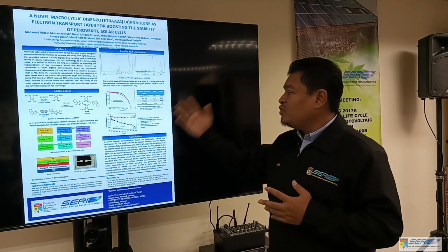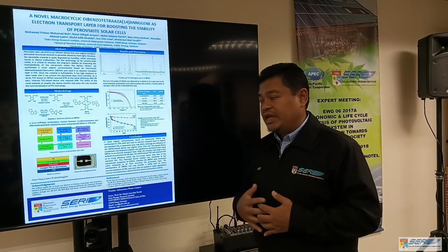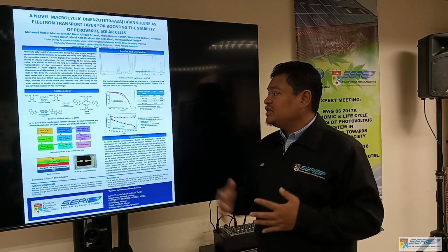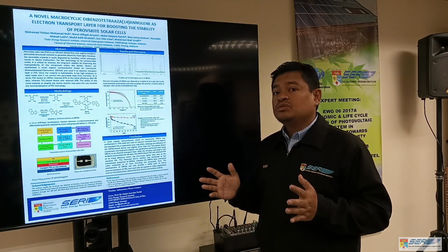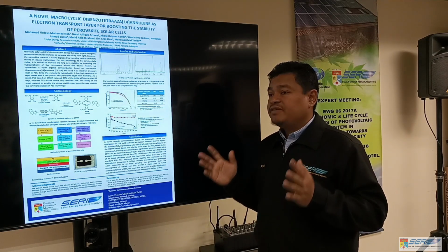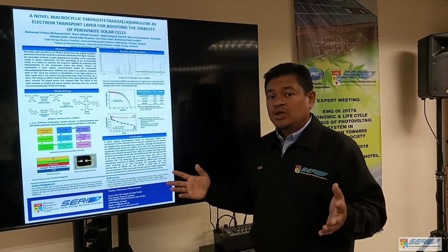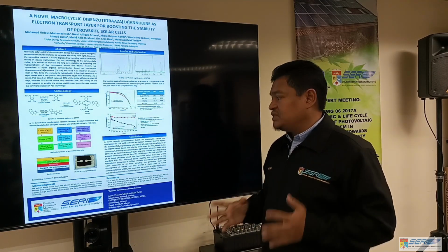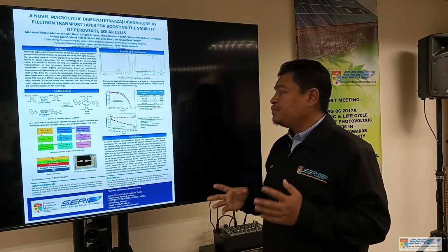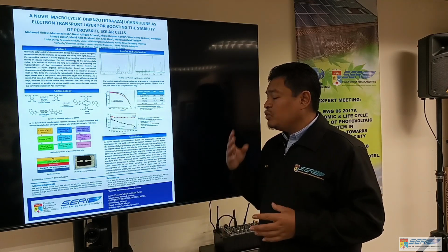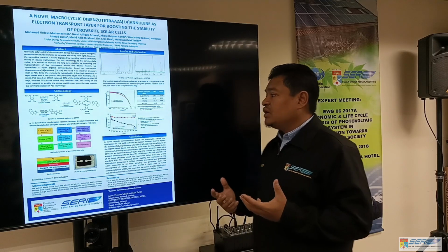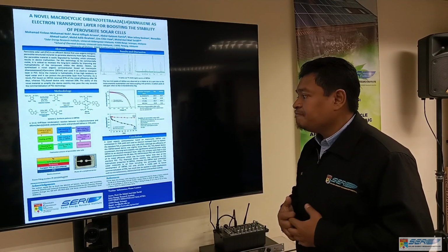But when we use our DBTAA, the stability is still maintained at 87% after 3 months, which is a very impressive result. That's why we are patenting this product.